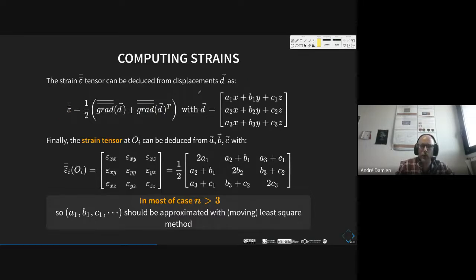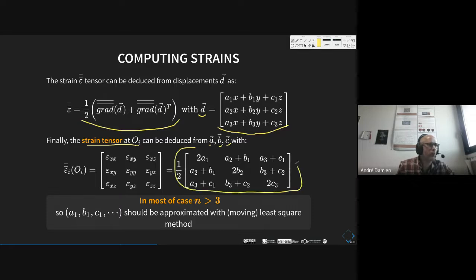So now, if we know the displacement of the neighbors, we are able to compute a kind of local displacement field of a central point. And from this local displacement field, it's quite obvious to compute a strain tensor, because it's given simply by this well-known formula. Here, the displacement field is what we computed at the step before with the least square method, or with the perfect solution if n equals 3. So finally, the strain tensor at the central point can be deduced from A, B, and C from this following formula. It's quite simple. We just apply the gradient on the displacement fields.